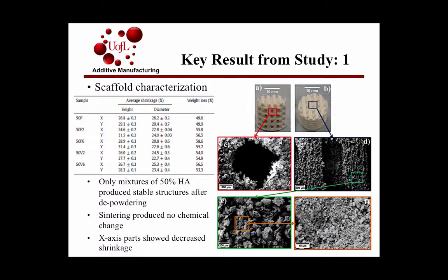And as you can see from the graph over there, the 50P, the 50F, and the 50V correspond to: P was just the printed, F was sintered in a furnace, and V was heated in a vacuum heater, and the 2 and the 6 correspond to the 2 hours or 6 hours of heating. And the X and the Y were the print direction along the axis, which axis they chose for the print direction. The X-axis parts for all samples showed decreased shrinkage, more uniform shrinkage between diameter and height. The Y-axis printed samples showed more shrinkage in the height than they did in the diameter. But they all were fairly similar in weight loss percentage, within 2%, which the study considered small enough to be viable.